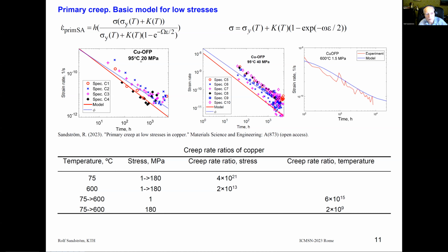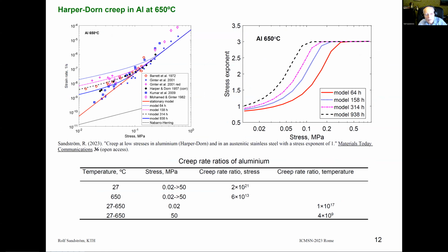And it's valid at high stresses, which I don't show, but it's also valid at very low stresses. And also, in the case for 600 degrees C, it's also valid at very low stress. And the interesting thing is you can use the same parameters at high stresses as at low stresses. And these represent an enormous extrapolation in the creep rate. And the same applies to changing the temperature. So it's many orders of magnitude extrapolation which takes place, and the model is still valid, and this demonstrates the validity of the model.